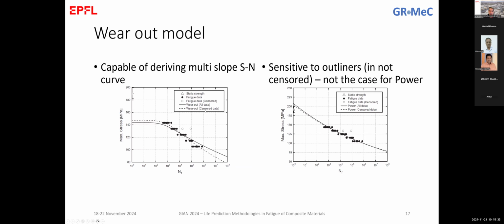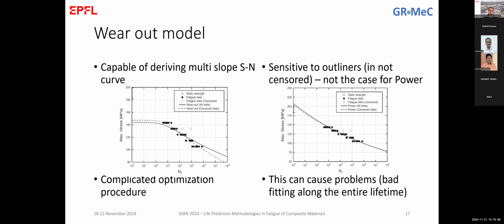And the same model with the censored data, so without assuming these two, is the dashed line. You can see only by observation that the accuracy is much better for the censored data set. So this is what we discussed, that you should be careful with outliers that affect the behavior. So the wear-out model, you see that it is good for the entire range of points, but